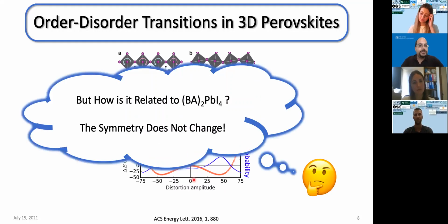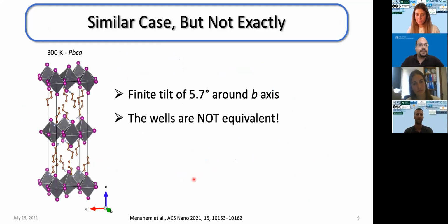But how is it related to butyl ammonium lead iodide? The symmetry of butyl ammonium lead iodide doesn't change during the phase transition. So going back to the XRD of the high temperature phase, we see that the octahedra have a small finite tilt around the crystallographic B axis of about 6 degrees. This tilt is what breaks the symmetry and keeps it at the lower symmetry, orthorhombic symmetry, after the phase transition.